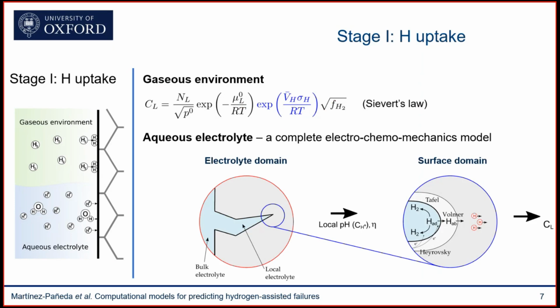The bad news is when you're looking at hydrogen uptake from aqueous electrolytes, such as seawater, for example, then the picture is much more complicated, because then you need to resolve not only the surface reactions taking place at the electrolyte-metal surface, but also the electrochemical behavior of the electrolyte, which can be very different inside of occluded crack environments, such as cracks and pits and other defects, relative to the bulk, which is where you typically conduct your measurements.